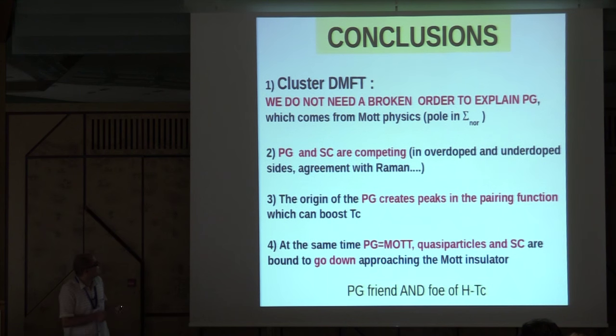Now, these are my conclusions. I hope to have shown you good evidence, at least for Hubbard models in 2 dimensions, that you don't need a broken state to explain a pseudogap. It doesn't mean that in reality you will not have a broken state. Ultimately, these broken states that originate from the pseudogap could help superconductivity. This is possible. I'm just talking about this Hubbard model. The pseudogap and superconducting gap look like they are competing for the same electrons, and they have different shapes and different responses to different probes. In the overdoped and underdoped side, we have compared with Raman. On the other hand, the origin of the pseudogap seems to shape superconductivity a lot as well and boost up Tc. So at the same time, this competition might be a friend and a foe for superconductivity.